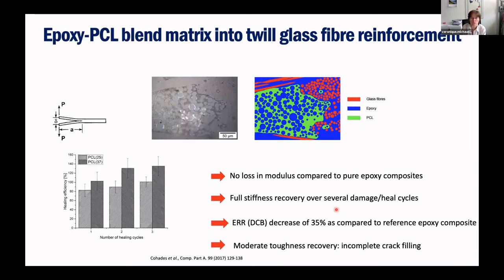So first thing is to look at what happens when you mix this epoxy-PCL blend into twill glass fiber, which is the workhorse of cheap glass fiber that we use in our lab. We saw that, of course, there is a sizing that is an epoxy-compatible sizing. So the epoxy phase tends to nucleate on the fibers, but the phase separation still takes place. We saw also that there is a bit of a change in the morphology of the phase separation due to the diffusion length between the fibers and so on, but it's still okay.